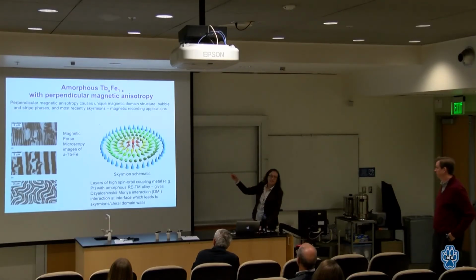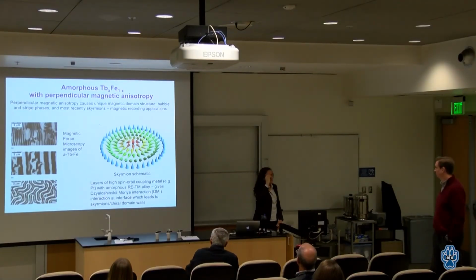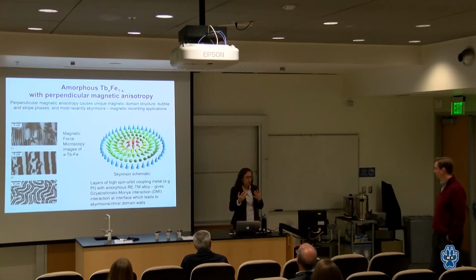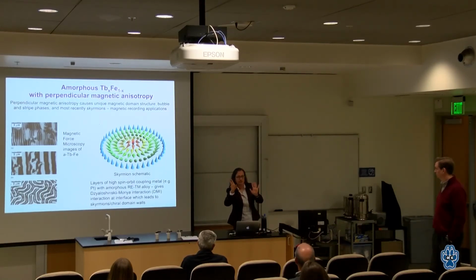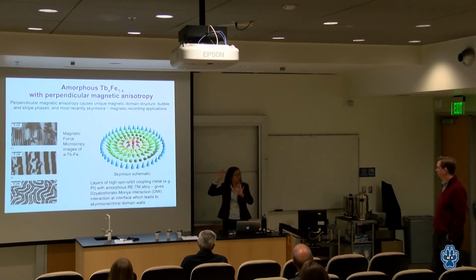Yes, and in fact, there's no length scale in this, this is just a schematic, but the size of a skyrmion has to do with a bunch of competing energies. So one of the energies is the usual magnetic exchange energy, which wants everything to line up. This spin orbit coupling with the platinum on the top wants things to be perpendicular. So that's one competition. This is always stronger than that, I think always. So this in general wins, but on a longer length scale, this adds up and makes it want to make a curl structure. There's also dipole coupling, which also, by the way, doesn't care about chirality, but it does want it not to be all just up, because there's a lot of dipole energy in that. So the size is all these different energies competing with each other.